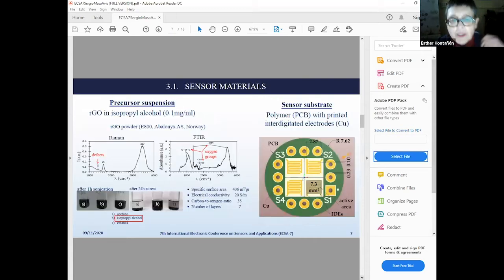And the material we have used, as I said, we start from a precursor solution of reduced graphene oxide in isopropyl alcohol with a concentration of 0.1 milligrams per milliliter. And the material, the reduced graphene oxide, is a commercial powder that is produced by Abalonyx, which is a graphene manufacturer in Norway. And after characterizing the powder with a number of spectroscopy techniques, it came out that the material has not many defects, it's not very defective, but has a lot of oxygen groups bonded to the carbon on the layers. So it's expected that this material should have some reactivity to gases.